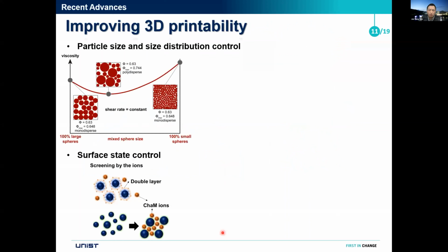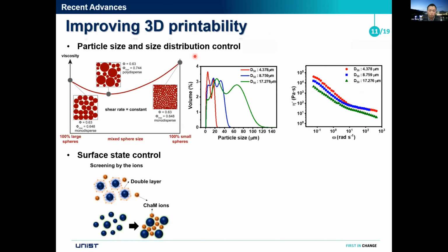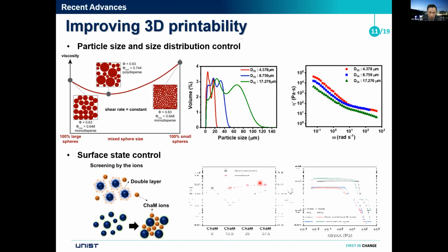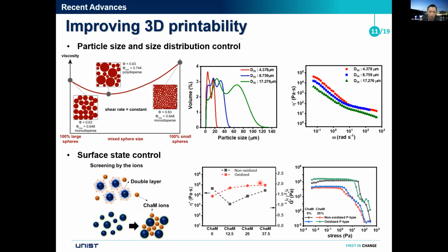And for better resolution of 3D printing, or for finer control of printed structure, we have to improve the rheological property of the ink further. To this end, we control the particle size and size distribution more precisely. We have used a smaller particle with a narrow size distribution and got higher viscosity. Also, we have precisely controlled the surface state by oxidation, and then we got very high viscoelasticity.